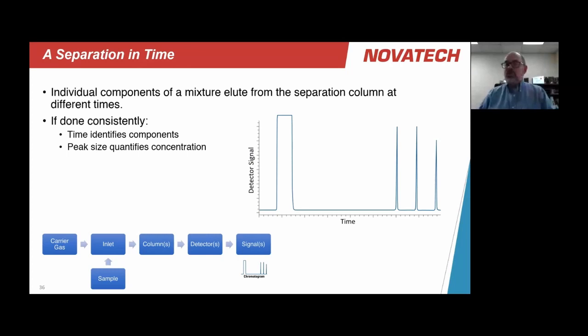So for example, when we're separating hydrogen from the mixture, at a predetermined time, we know that hydrogen will come out, and we know that the area under the peak that's generated at the detector is proportional to the concentration. The only thing it can be is hydrogen.